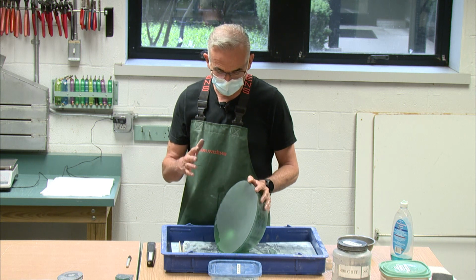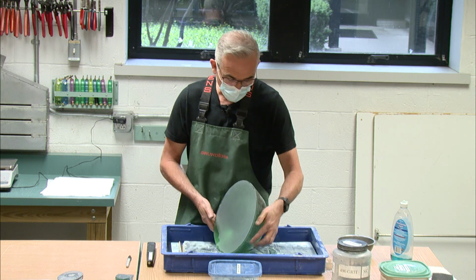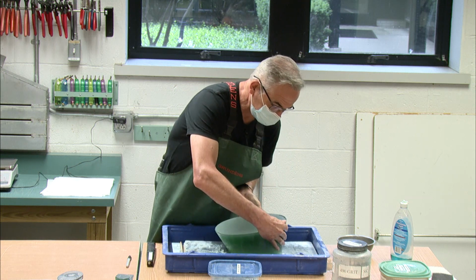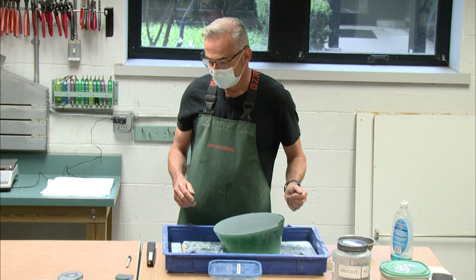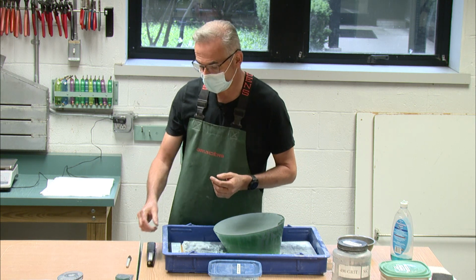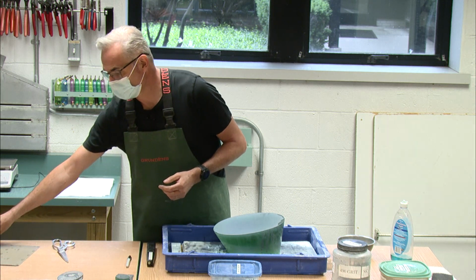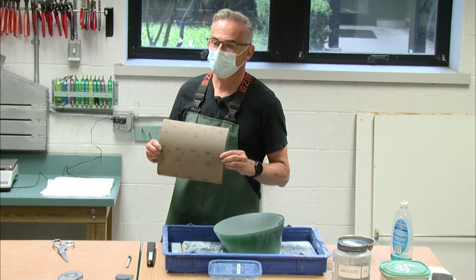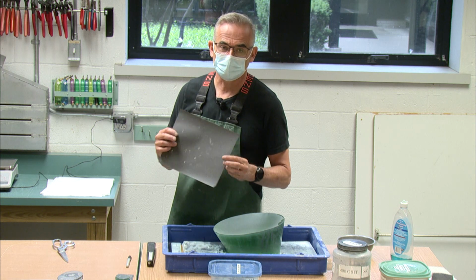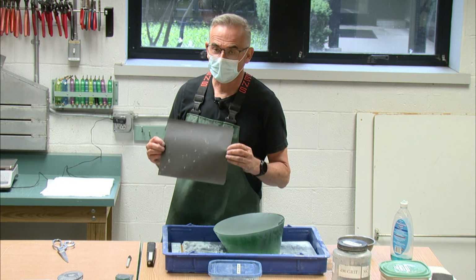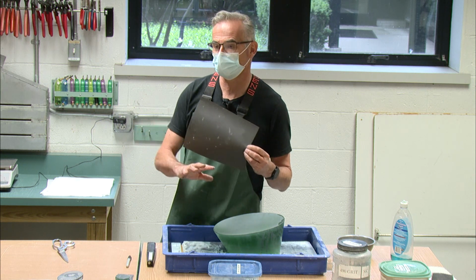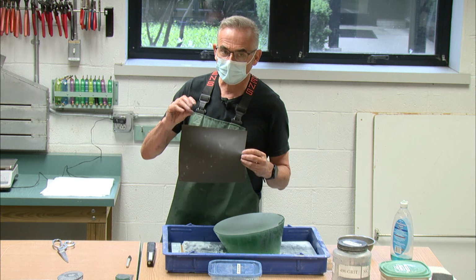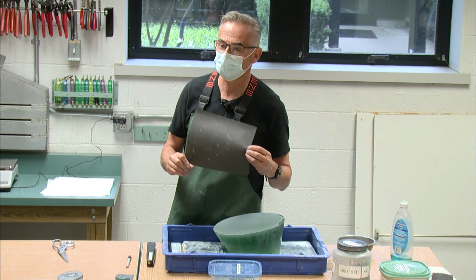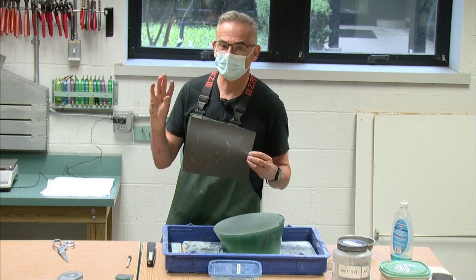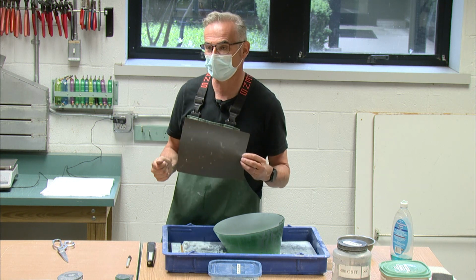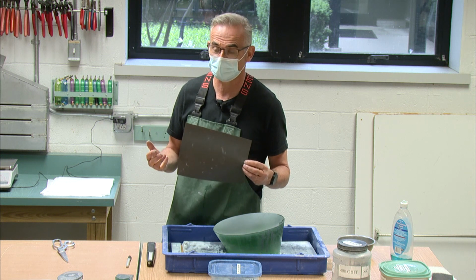The first thing I'm going to do is I'm still going to use the same grit, but instead of using glass on glass, I'm going to use emery paper. So this is just 400 grit emery paper that you would get from the hardware store. It's really a cheap material, and all that does is help us push the 400 grit across the surface. The backing part of that, the thing that's going to push it across the surface, is my hand. And my skin is much softer than the glass itself, so that'll give us a very different finish.